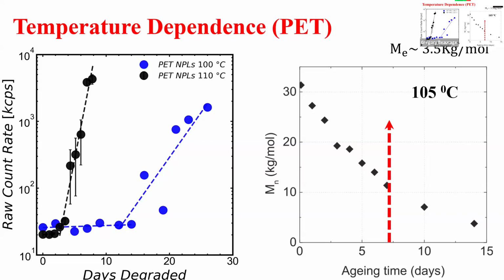So one thing we did do is focus not at 100 or 110, but at 105, because that's sort of in the middle, right? At 105, if you believe this, the degradation time is going to be like 7, 8 days. So we said, let's go do a detailed study. At 105C, we took our PET sample, degraded it in water, took the polymer that was left behind and measured its molecular weight. That's the molecular weight as a function of time. At 7 days, which is where you start making micro nanoplastic, the molecular weight we got was about 12 kilodaltons. Okay? Why did I do that?